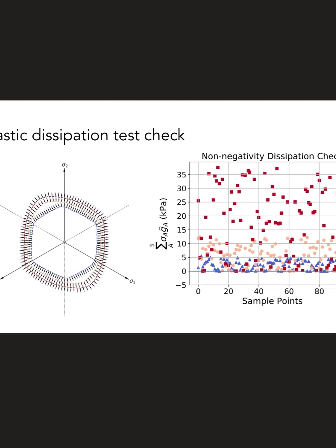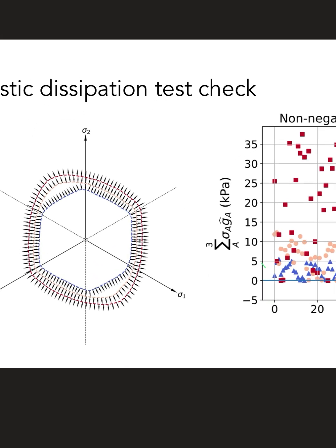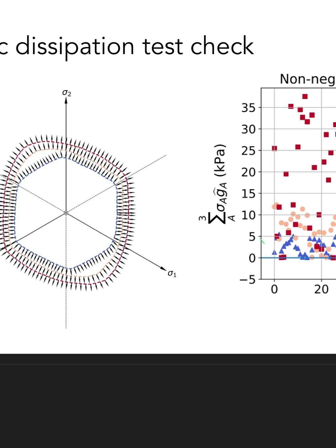Okay, so this is the check. And this is the enforcement. As you can see, a lot of the loading. These are three different colors indicating a real polycrystal material getting yield, and it mainly has isotropic yielding, but it has some distortions. Okay, it translates a perfectly symmetric loading to something that is no longer symmetric, or symmetric in these directions. You see, initially the symmetry is here, but it's spun a little bit. Okay, so this is something I think is quite interesting, at least for me.